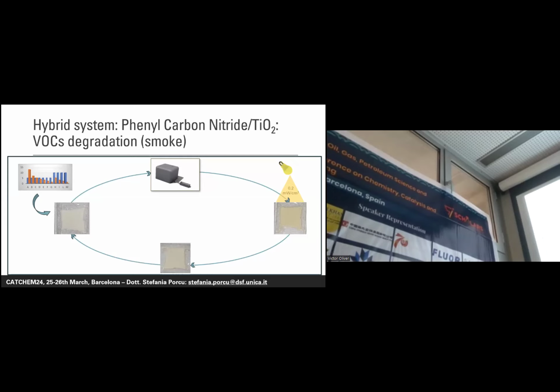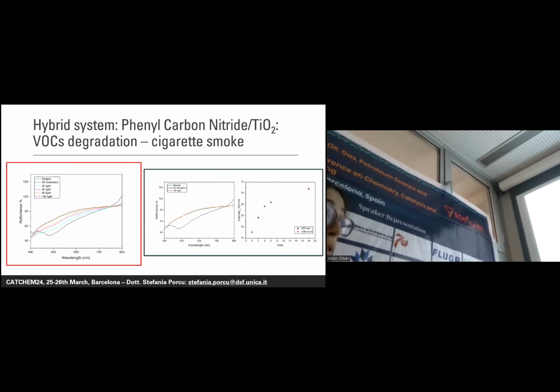Then we shine the light for different hours in different conditions, and we monitored the experiment through reflectance and colorimetric measurements to see how the degradation of the smoke pollutants occurs. The results are more or less summarized in this slide.